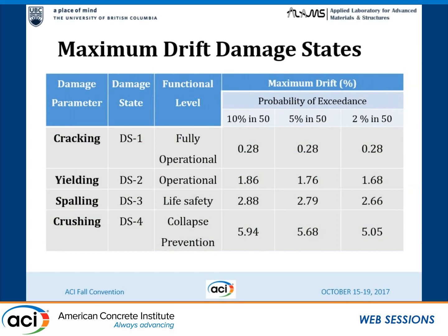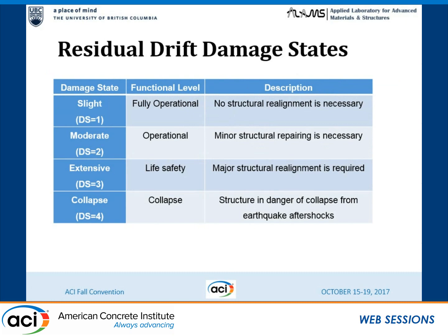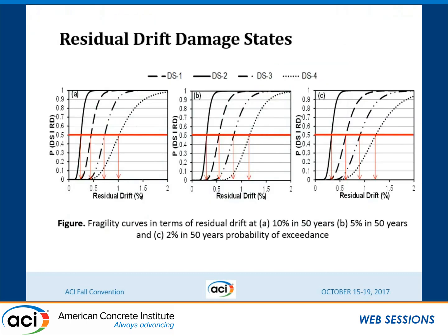For the nickel-titanium alloy, which is the most common, we can define damage states for different return period earthquakes. From field studies, it has been observed that residual drift can be directly related to damage level. It has been observed that if bridge columns experience more than 1% residual drift, it can be considered collapse, as it is not repairable — the bridge must be replaced. Based on various field data and experimental studies, we proposed residual drift-based damage states: fully operational at 0.25% residual drift, operational at 0.5%, life safety at 0.75%, and collapse at 1%.